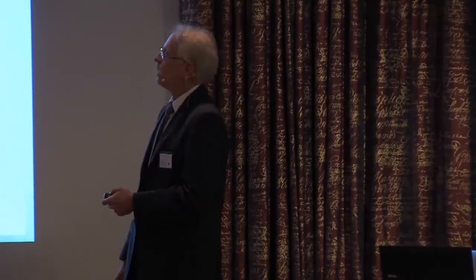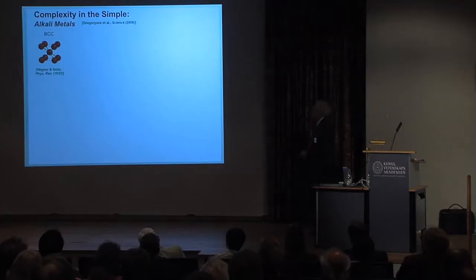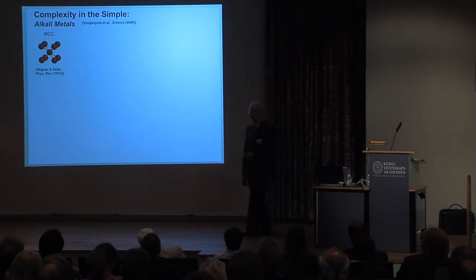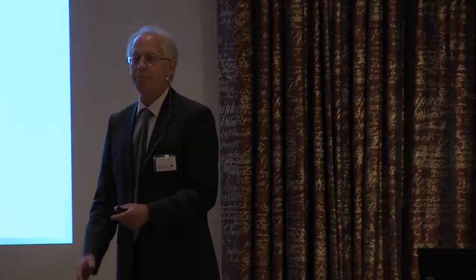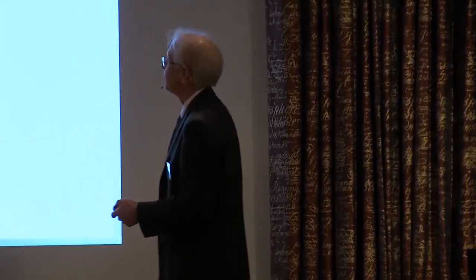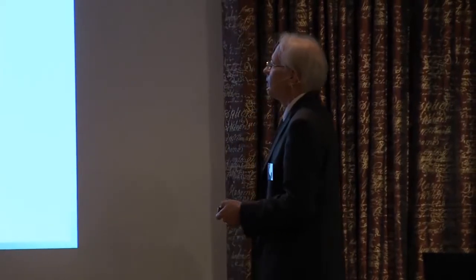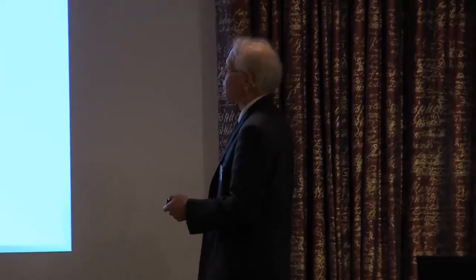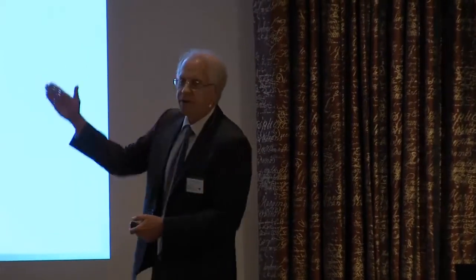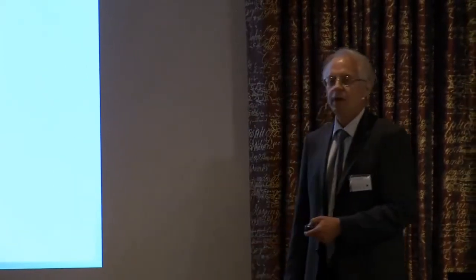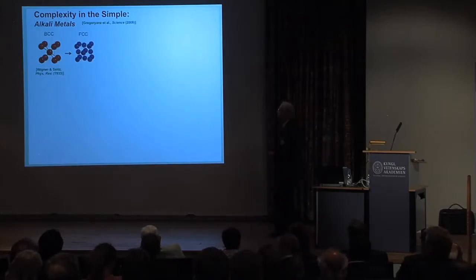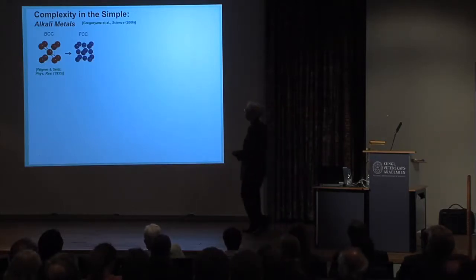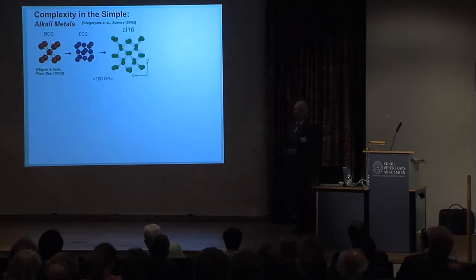But it's really much more complex, and the best example of that is what's been seen just in the last few years in another system, alkali metals, which for many years were considered the textbook example of the simple metal, the free electron metal. And this goes back to the classic calculations of Wigner and Seitz for sodium, for lithium, assuming this BCC structure. With increasing pressure, initially it goes to another structure that's quite symmetric, a close pack structure, FCC. But when one reaches roughly megabar pressures, one sees this emergent complexity.